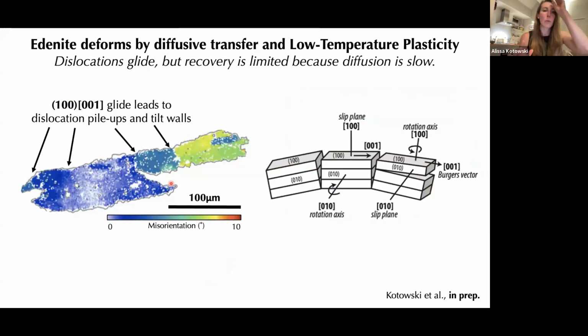And that's because we already had evidence for diffusion accommodated deformation in the form of the core to rim zonations, that metamorphic growth. But we also have evidence for this dislocation glide here in the form of these subgrains and tilt walls. So if we look at the orientation of these subgrain walls, this looks like easy glide along the A plane in the C direction.